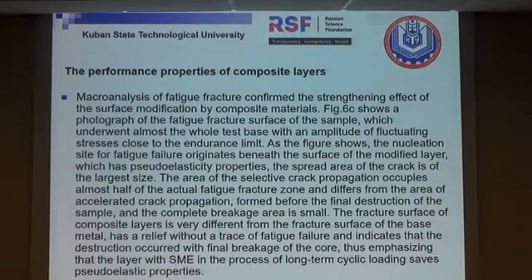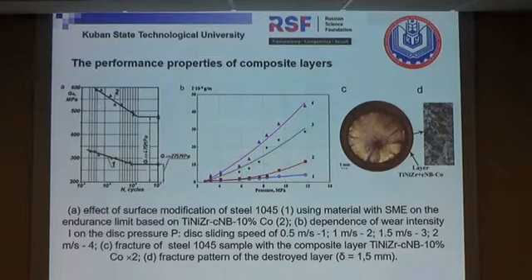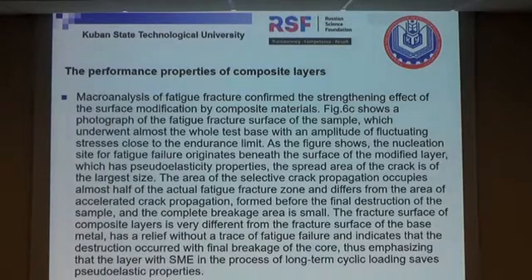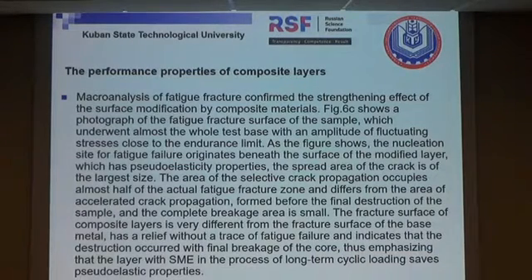Macroanalysis of the fatigue fracture confirmed the strengthening effect of the surface modification by composite materials. Show these photos. They show the fracture surface of the sample, which was tested in rotating bending with an amplitude of fluctuating stress close to the endurance limit. As the figure shows, the initiation site of the fatigue crack originated beneath the surface of the modified layer, which has superelastic properties. The slow-growth area of the crack is of the largest size.